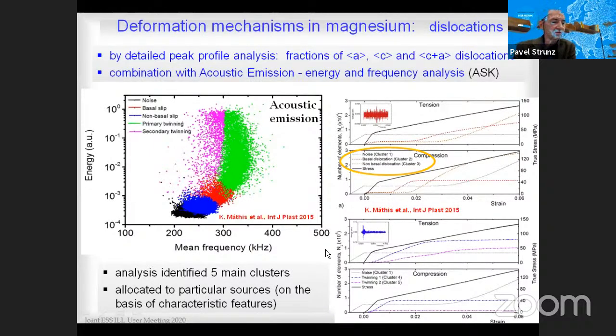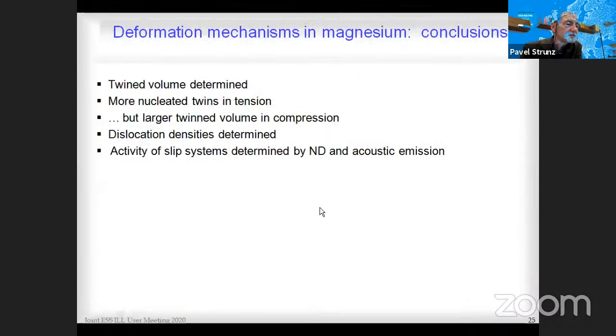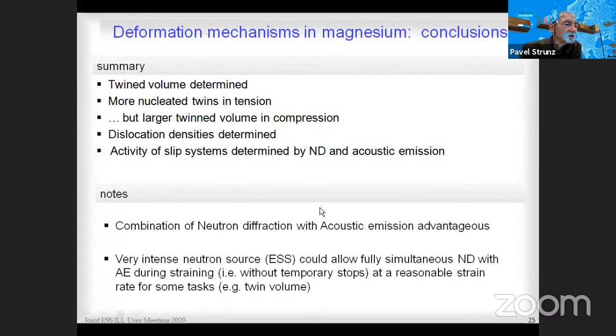I will not go into the very details of this research, and I would like at the end of this part to tell two notes. First is that the combination of neutron diffraction with acoustic emission is very advantageous, and second, a very intense neutron source could allow fully simultaneous neutron diffraction with acoustic emission during straining at some reasonable strain rates, for some tasks like twin volume determination.